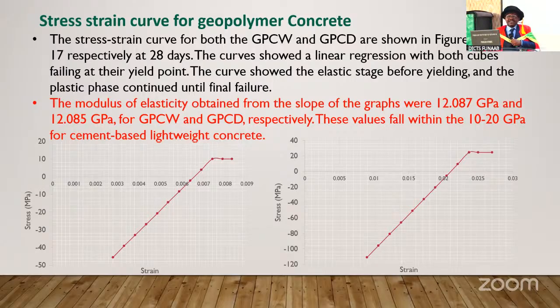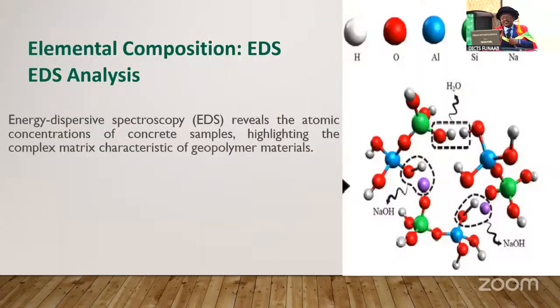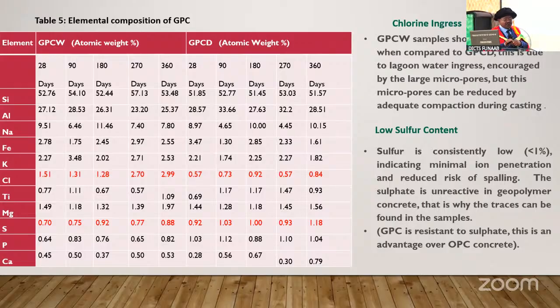Now we look at the elemental composition of geopolymer concrete. From table 5, our interest here is chlorine and sulfate, which are the enemy of concrete. Here, GPCW samples show high chlorine content when compared to the GPCD. This is due to lagoon water ingress encouraged by the large micropores. But these micropores can be reduced by adequate compaction during casting.